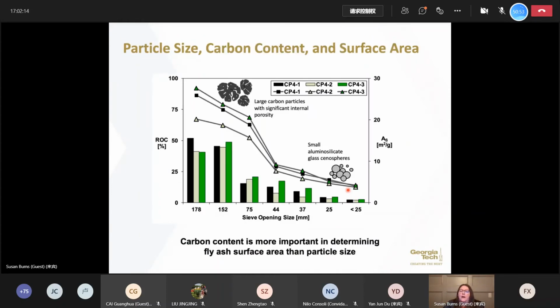So let's think about why this happens. Essentially, what you'll see is that when we look at grain size, going from largest openings to smallest here on the right-hand side, and then we think about our residual organic carbon content, we can see here in these cases that at the biggest particle sizes, we have these very large carbon grains. And those carbon grains have very large internal porosity, and that surface area is going to be available for uptake of contaminants and a variety of other sorbents.